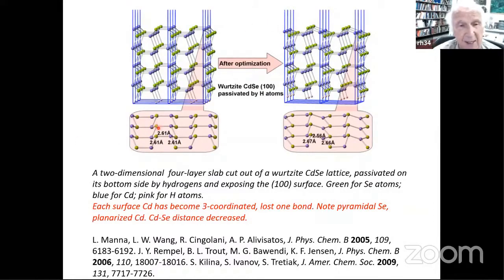You see here in the unreconstructed structure of that surface, the purple here, or blue, is the cadmium, the green is the selenium. You see this in this cut out of the solid, the selenium remains pyramidal and the cadmium next to it remains pyramidal. I go over to the surface. When I allow it to relax, look what happens. The cadmium goes planar on the surface, every cadmium. But the cadmiums underneath don't change. The selenium goes, that's not obvious, actually more pyramidal than it was. And the distance goes down a little bit. This is the sodium chloride story. There is some better pi bonding in this adjusted structure.